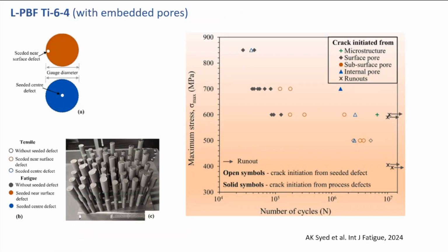And then the last study we did is the laser powder bed fusion, which confirmed a very similar story. And the location, these black diamonds are all near the surface. We call them surface pores or subsurface pores. But the round ones are internal pores. So I think I just move on quickly.